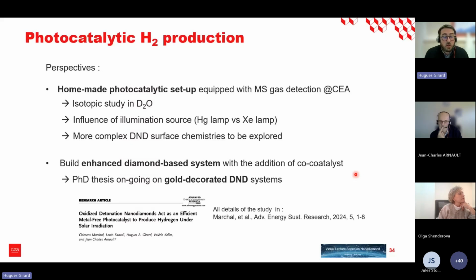At the same time, we also want to build more complex, diamond-based systems with the addition of co-catalyst. This is what is usually done with titanium dioxide and all the other types of photocatalyst, and so we started last year with a PhD, and we are working on a gold-decorated detonation nanodiamond system, for which we are starting to have very good results. So here is the paper in which you can find all the details of this study.